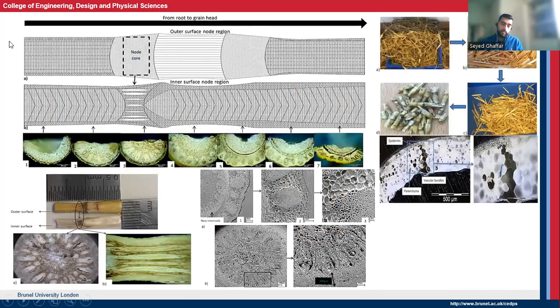So this is the microstructure of the node in the wheat straw as cut longitudinally. And you can see how the cross-section looks when you go from the bottom, to the direction of the root, from the root to the grain head. So you have the cross section at this part, and you can see it changes, it becomes very compact, and then it enters the upper internode. These are some more optical microscopy and scanning electron microscopy images of the node.